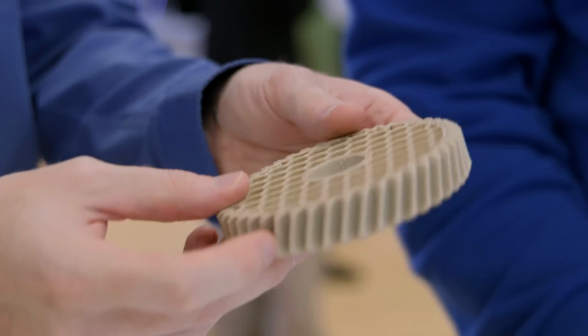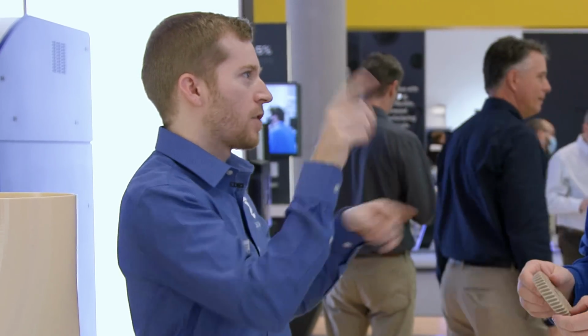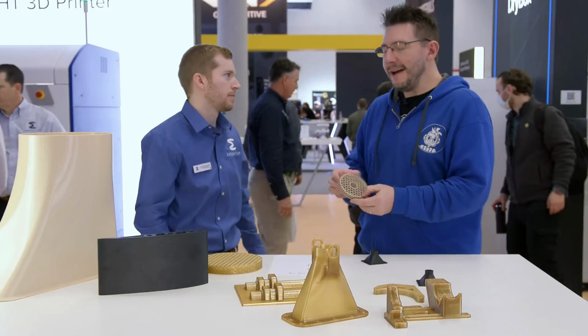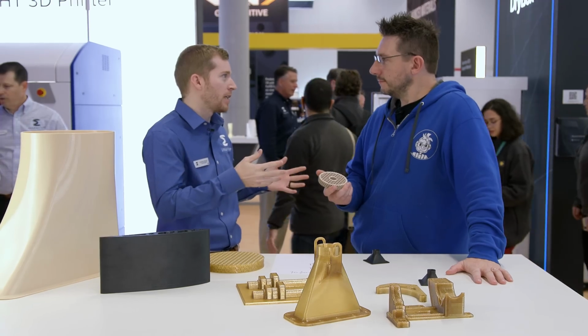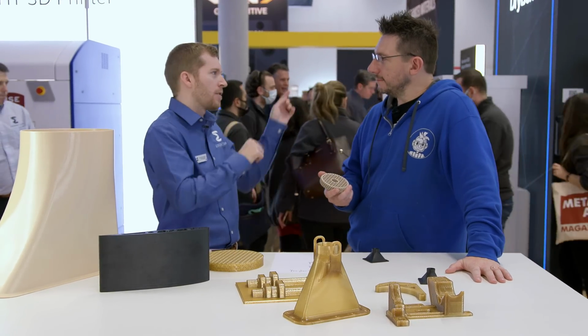Well, I've noticed when annealing PLAs, they become more opaque. Yep. And that's because things line up and it becomes more semi-crystalline. Those spherulites grow and they actually scatter light. The light just bounces around, so it's no longer clear. The light doesn't just go straight through. Oh, that's cool. PMMA, glasses, polycarbonate, those are all amorphous. The light goes straight through it. There are no crystalline regions to scatter the light.